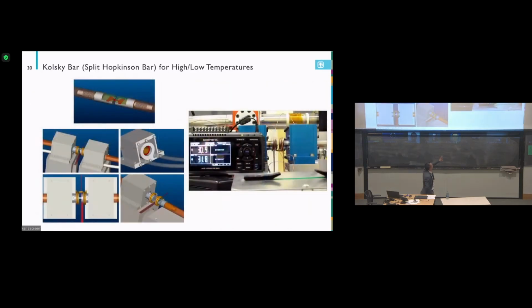So we use an induction heater. We pre-install the sample to the bar and use the induction heater to heat the sample. Yes, we also heat the bar a little bit, but how do we drop the temperature? So we designed a cooling block. That's the blue one. It's hollow and has cool water circulating inside. We force the bar temperature to room temperature or even below room temperature. Then we run the dynamic tensile test.